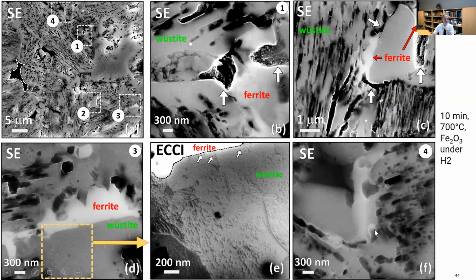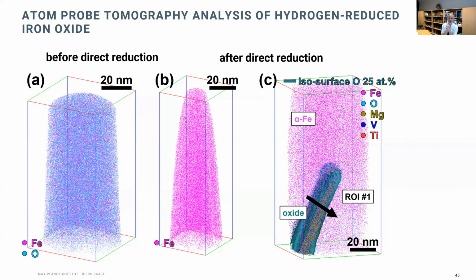And of course, through the loss of oxygen, you also build up diffusive porosity. So it's a real complex universe that you want to understand in detail. And we can even go a little bit deeper. We can go to the atomic scale if we have to, through the atom probe tomography group of my colleague, Professor Baptiste Gault. And this is a measurement by Seho Kim and Ayman El Sokka, where they look into the atomic state of these oxides.